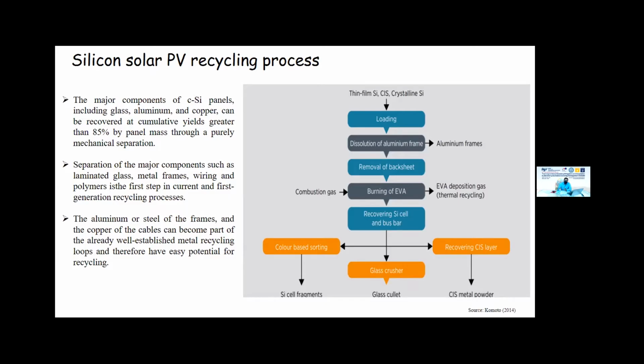But this is not an issue, because we can recycle our materials. We can see that the major components of the crystalline silicon panel, including glass, aluminum, and copper, can be recovered at a cumulative yield greater than 85% by panel mass through purely mechanical separation. If we do the mechanical separation, then 85% can be recovered, along with separation of the major components such as laminated glass, metal frame, wiring, cable, and polymers.